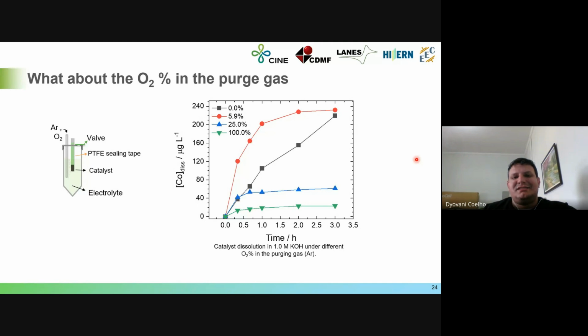And this happens when we are just trying to change the oxygen concentration in the purging gas. If we use no oxygen in the purging gas, like here in the black line, we can see a linear dissolution of cobalt over time, which means that the cobalt is just dissolving over time. But if we put a little oxygen in the purging gas, like 6% more or less, here in the red dotted line, we can see that the behavior is different.